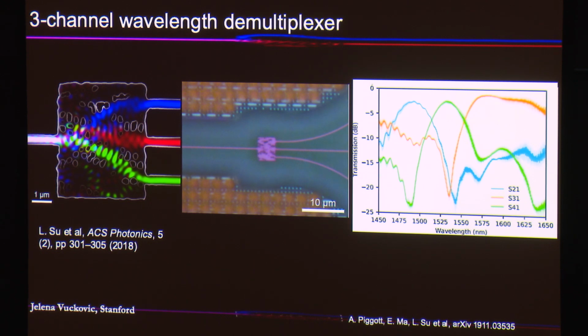There is a tiny bit of discrepancy coming from the fact that we designed for 80 nanometers and not 90 to 100. And it's pretty comparable to what we saw in e-beam lithography.